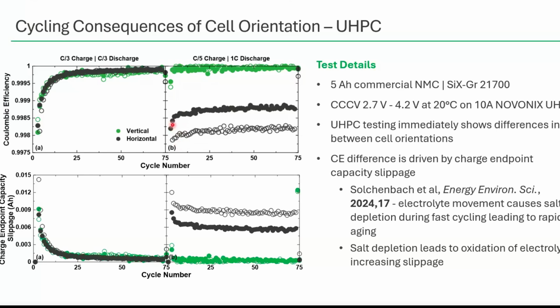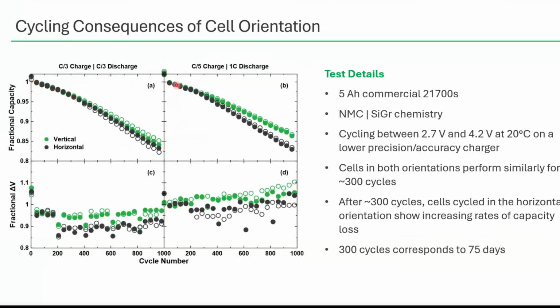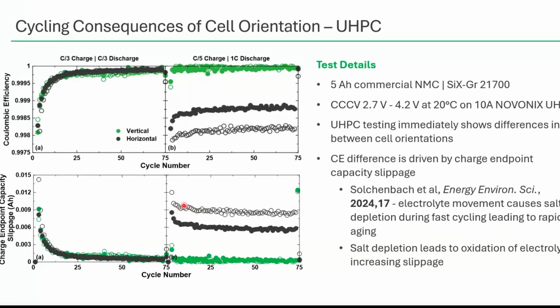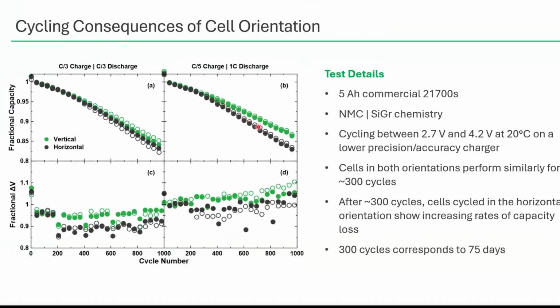We already know that the capacity fade is the same between vertical and horizontal orientations in each of these cases, because that's what we saw early in the first few hundred cycles. So we're not even going to look at capacity fade here - we're just going to look straight to charge endpoint capacity slippage. This is really interesting, because the coulombic efficiency difference between vertical and horizontal cells is driving a difference in charge endpoint capacity slippage. These horizontal cells with faster discharge are experiencing more of these slippage-based mechanisms somehow, and this eventually leads to worse performance and a divergence later on that takes hundreds of cycles to show up.